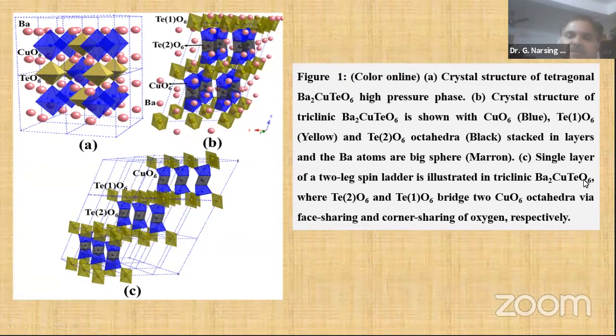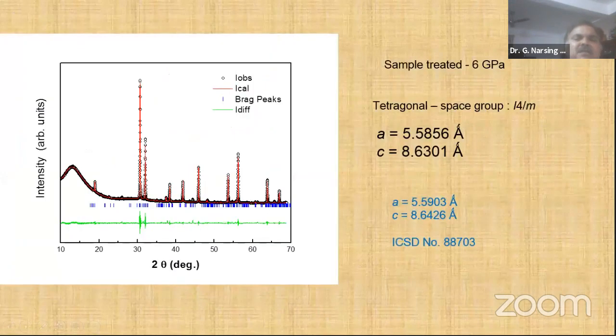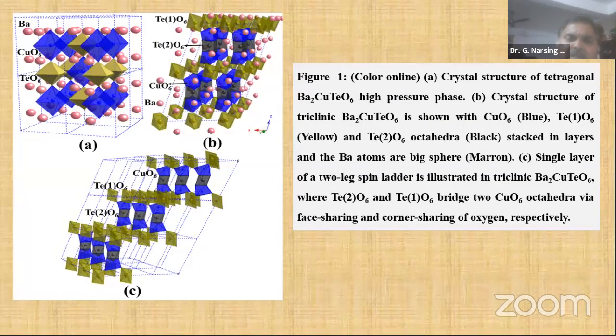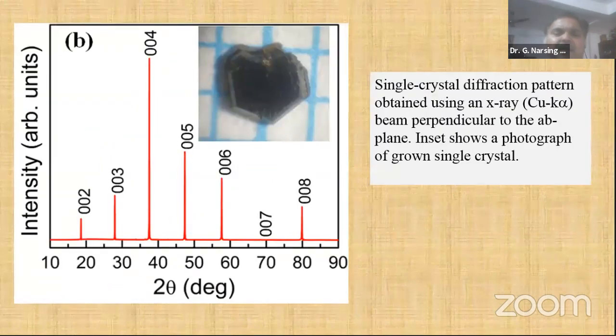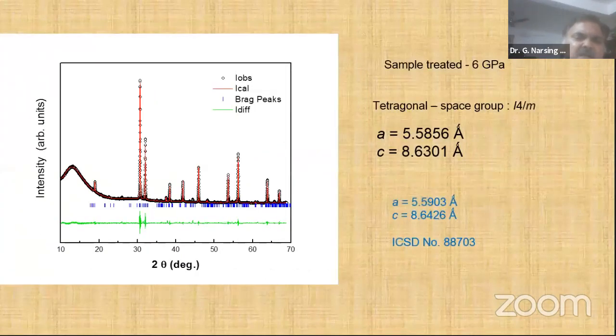It's Ba2CuTeO6. So you can see this structure. We make this at a high pressure state. Same material, the same Ba2CuTeO6 crystals. We make it at high pressure, then it comes out as a powder. That high pressure one shows a tetragonal structure, and the as-prepared one is triclinic: tetragonal and triclinic.